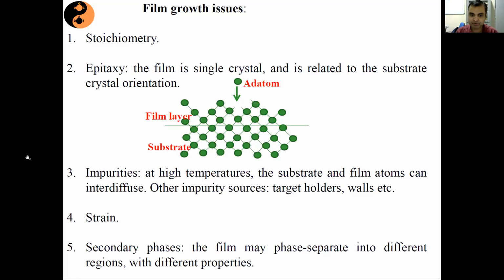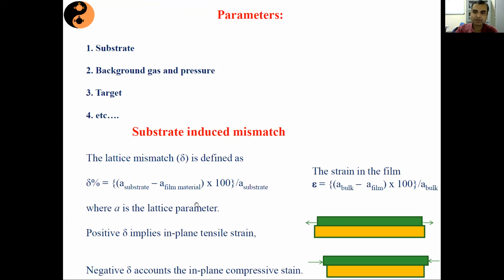Then secondary phase is also one important issue I just discussed in terms of BiFeO3. Suppose if I have to prepare a film of BiFeO3, then of course I do not want that in that film there should be contribution of bismuth oxide or Fe2O3 or Fe or any other phase. Okay. So what are the parameters which control these thin films? One is the background gas and pressure, the substrate that we have chosen, and the lattice mismatch. As I said, that it tries to fit, then the lattice mismatch is given by substrate lattice parameter subtracted by film material's lattice parameter, divided by the substrate lattice parameter, into 100.